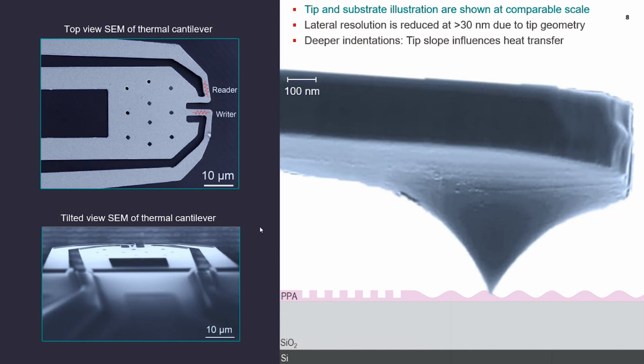So for example, patterning at peak-to-peak depths larger than 30 nanometer significantly reduces the lateral resolution due to tip's conical geometry, basically. And for deeper indentation, in addition to tip apex, the slope of the tip, as you can see here, also plays a role in the heat transfer, therefore preventing the fabrication of closed space pattern and limiting the aspect ratio of the fabricated nanostructures, or at least in the written nanostructures in thermally sensitive resins.